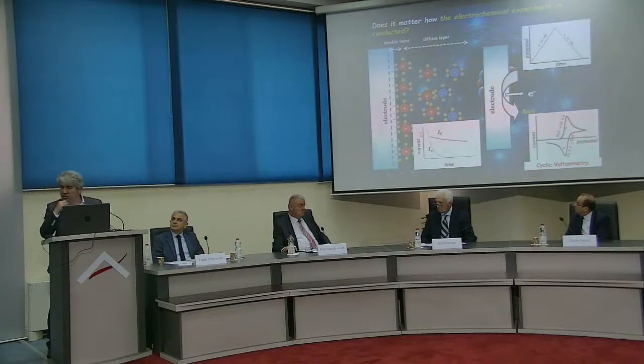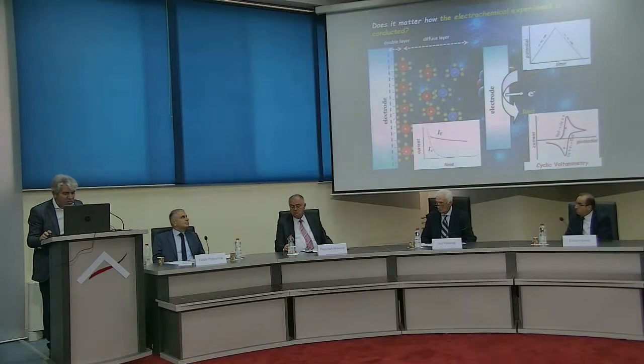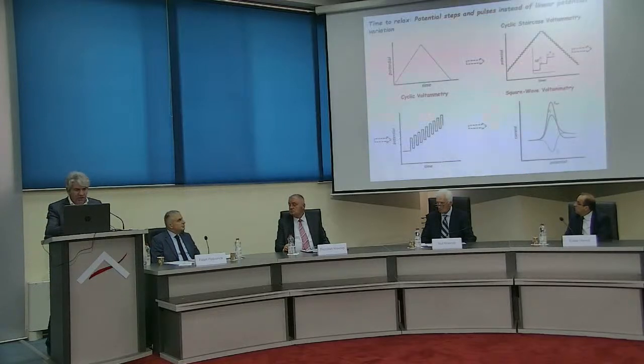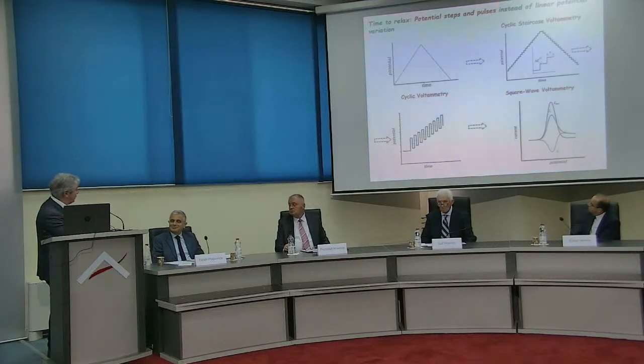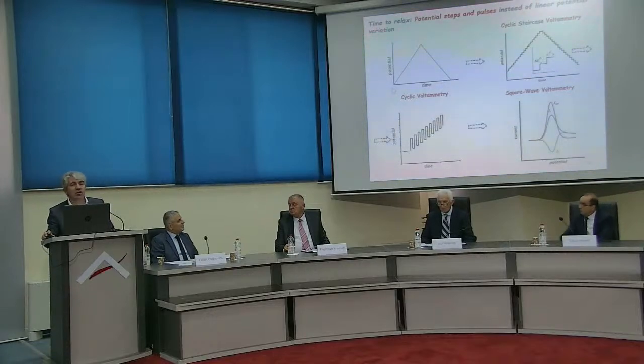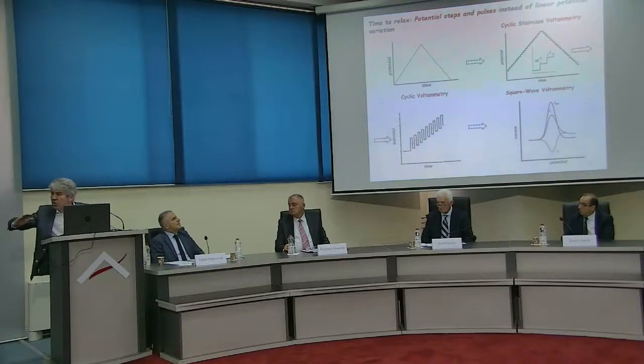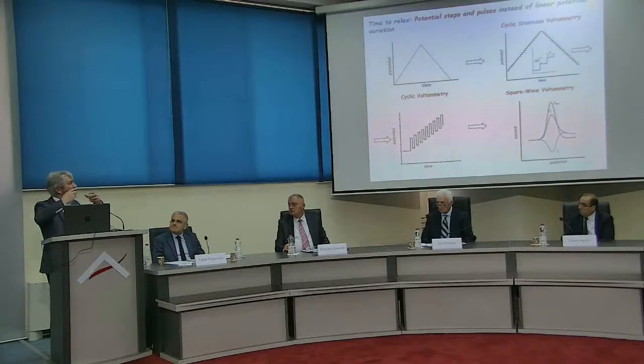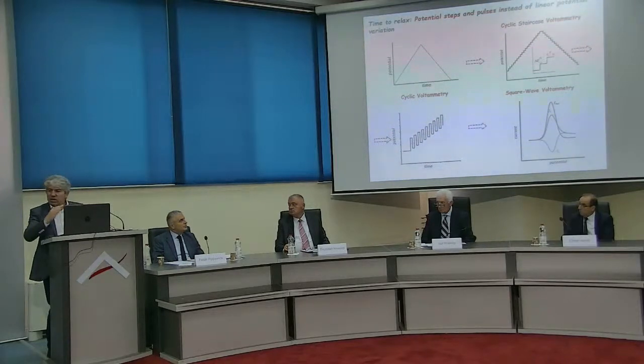But of course, it is known since long that with certain time, at constant potential, the charging current will significantly decrease. We are going to lose the Faradaic current also with time, but not so severely as the charging current. So that is why it is always good to relax a little bit, in life and in the electrochemical experiment as well. Not changing the potential just continuously, permanently, but let us do it in a stepwise manner. We apply potential and we wait a little bit. And at the end of this step, we measure the current, when the response due to capacitive current, as a priori unavoidable phenomenon, will decrease.